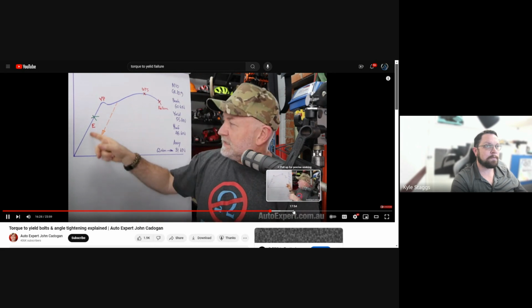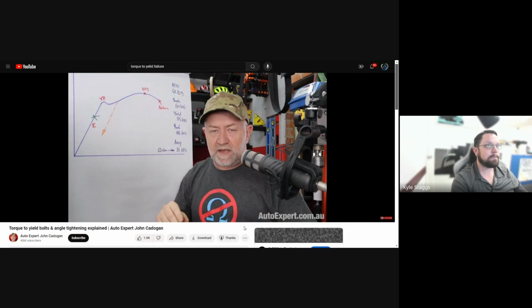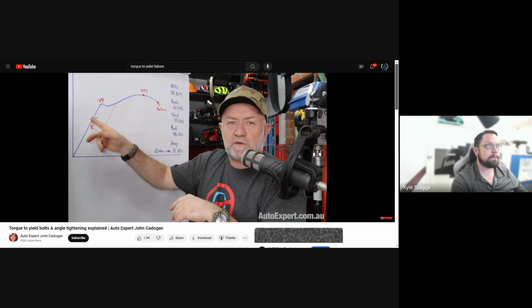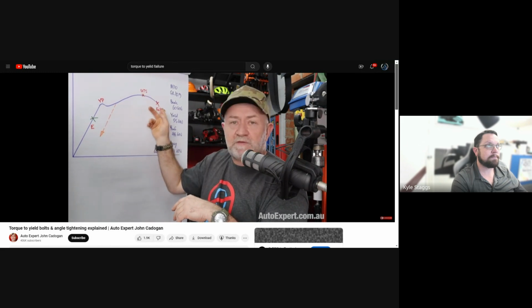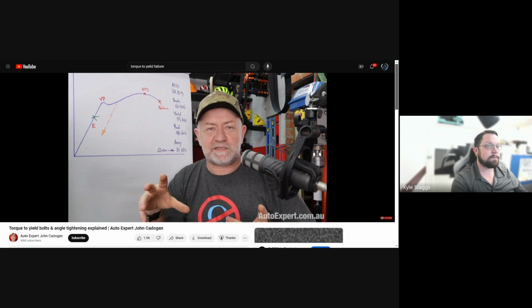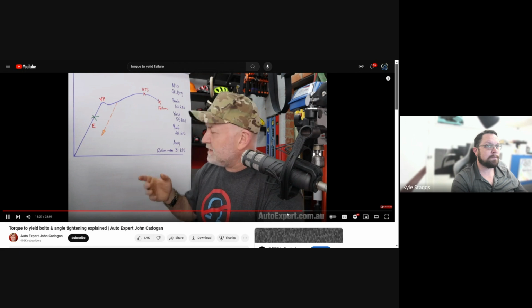What we're doing essentially with torque to yield bolts, torque, which they specify in the manual for these things, is about here. It's at like 31 kilonewtons, which is like 3 tons. So these are very conservatively loaded components, right? 3 tons worth of assembly for 6 tons worth of here, where it's going to fail, all right? And that's why they don't break very often, because they're so conservatively tightened. Incidentally, it's going to be about 63 newton meters, which is about 46 or 47 foot-pounds, I think, for an M10, grade 10.9 at the assembly torque operating about here.